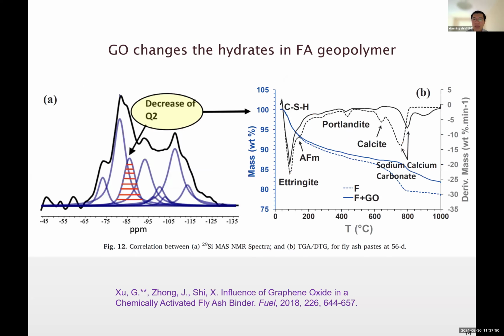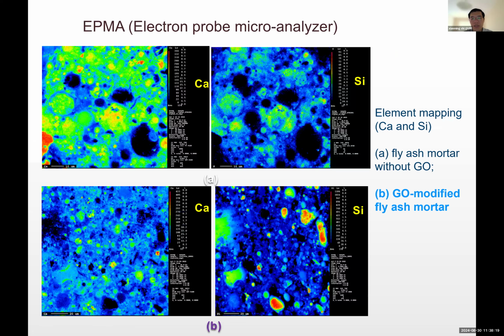So now we actually could use different tools to shed light on different pieces of the puzzle and reveal the whole picture. For instance, on the left-hand side are the NMR results showing the graphene oxide reduces the Q2 type of silicate. And on the right-hand side, this is a TGA or differential TG. And basically, they collaborate and tell the same story. Now, there's another tool we use, which is EPMA or electron probe microanalyzer.